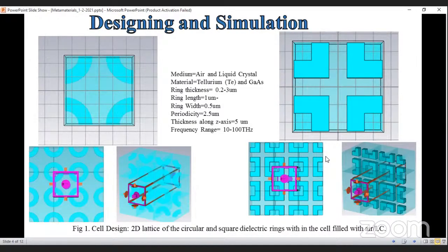So circular and square rings are placed in the XY plane, filled with air and liquid crystal medium. Here we used periodic boundary conditions applied in the XY directions, and the electromagnetic wave is incident along the Z axis with polarization along the Y direction, and the magnetic field along the X direction. These are the parameters we used for designing the structures. Here we vary the thickness and orientation of liquid crystal molecules at a constant periodicity of 2.5 micrometer.